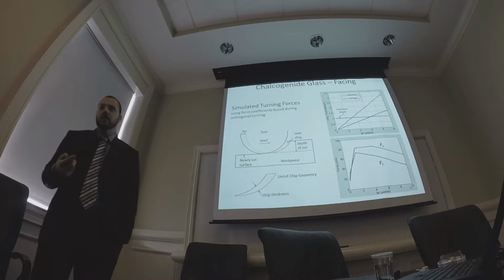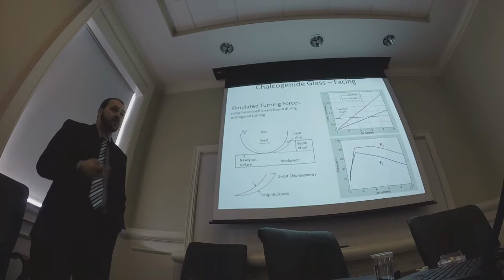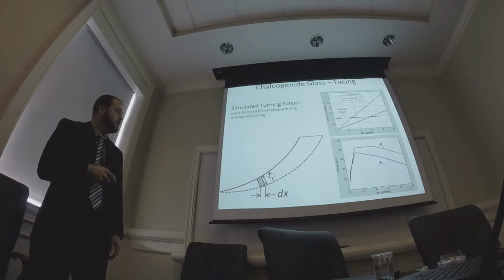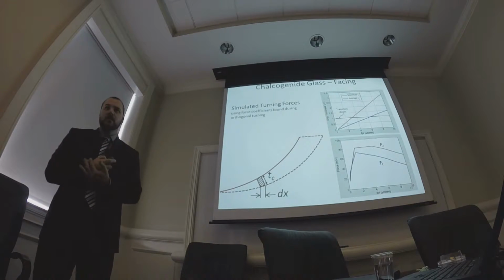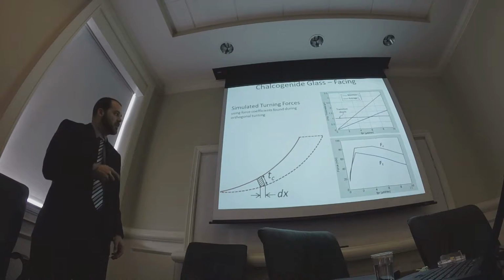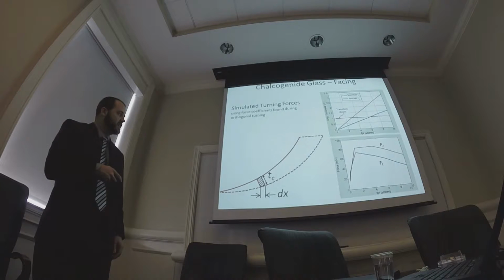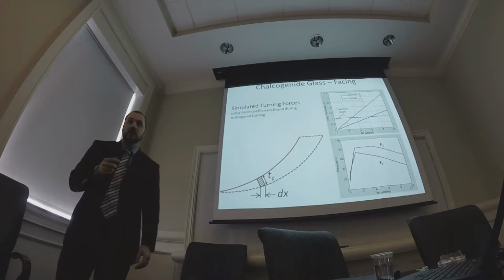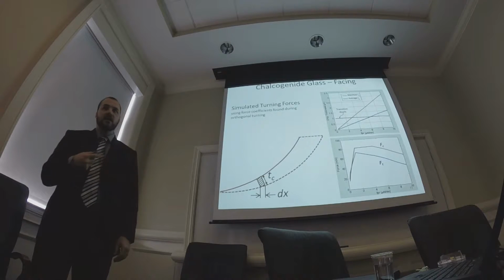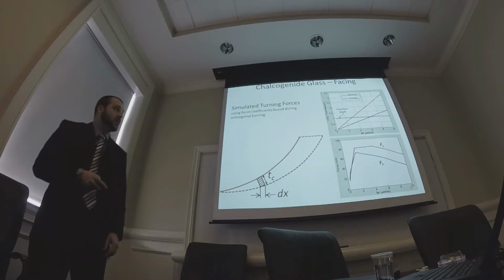So now we want to use our orthogonal cutting results to predict those forces. We take the geometry of the cut, and then we calculate the chip thicknesses along here. The way I did it is I picked the point here and found the minimum chip thickness everywhere along the tool, then did a numerical integration by multiplying this chip thickness and this dx, which is my change in width. Multiply that by the cutting force coefficients that I found in the orthogonal cutting.